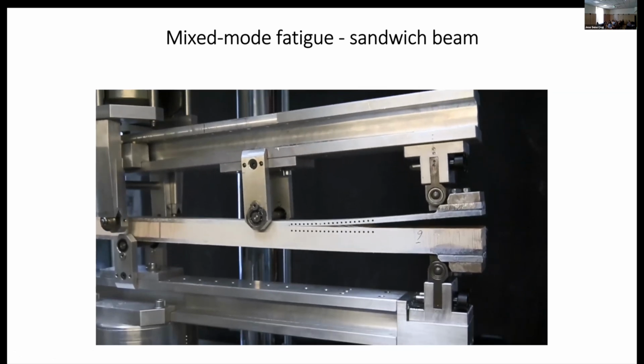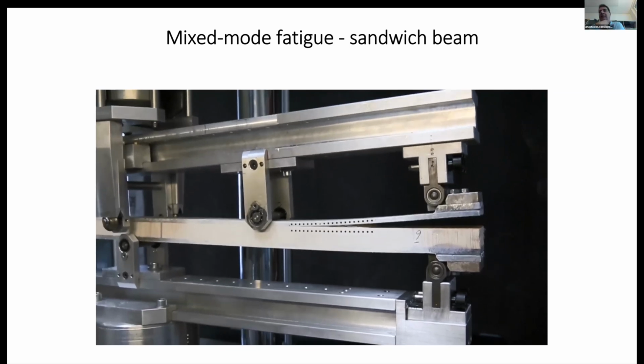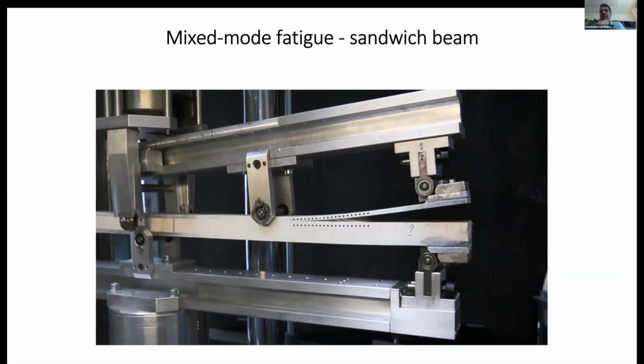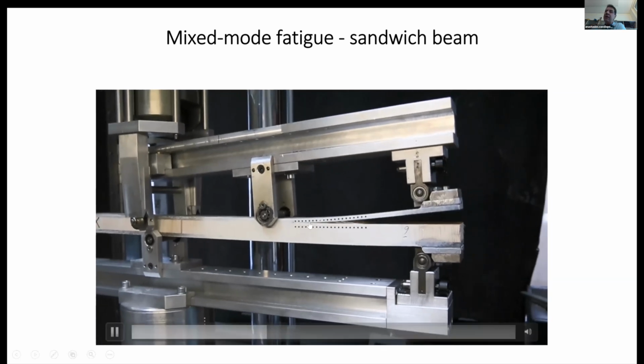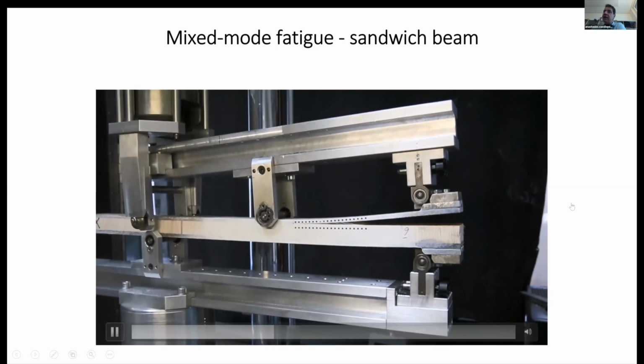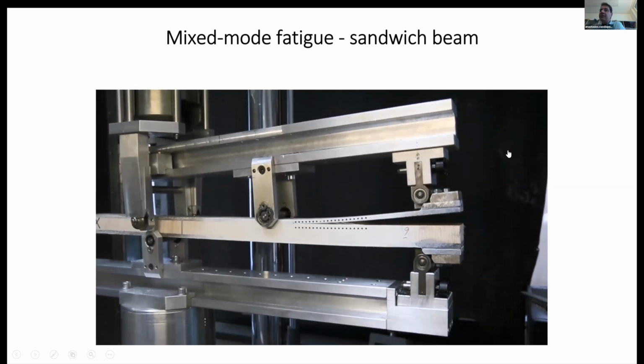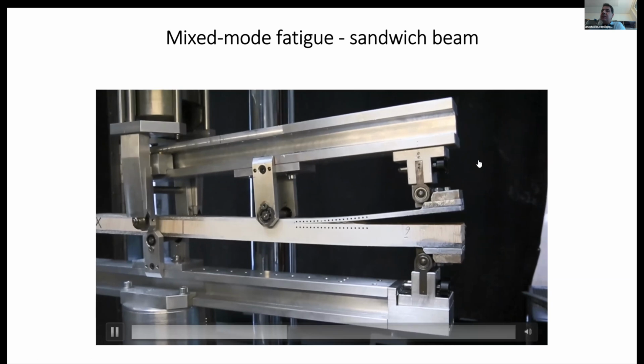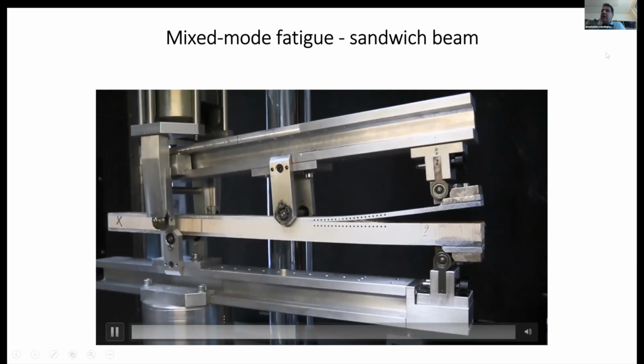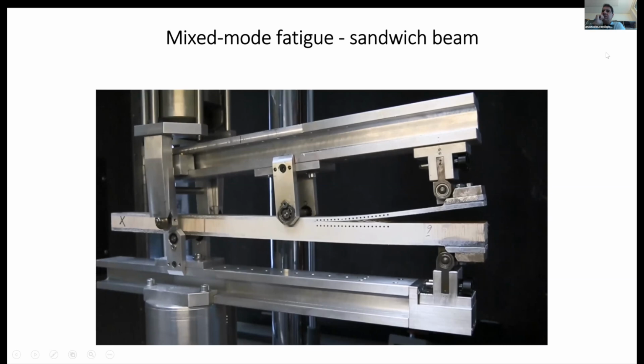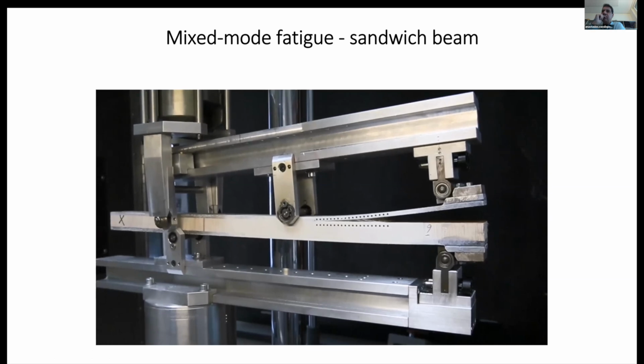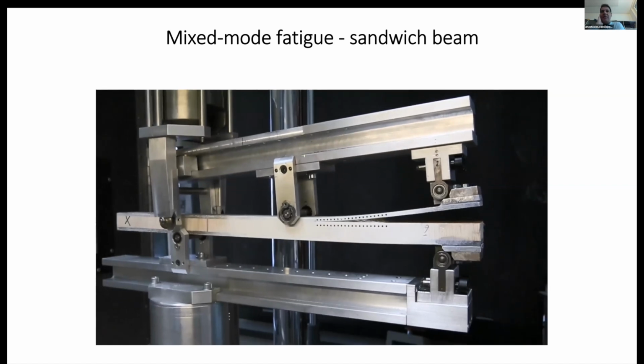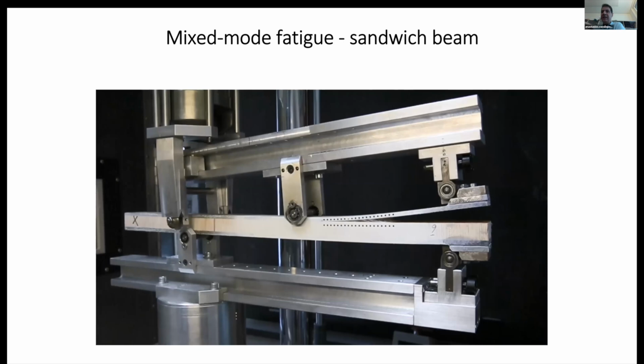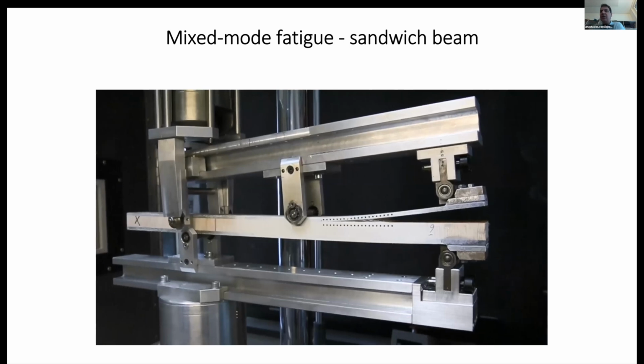So if you are interested in fatigue, you have to be patient and wait until this structure here reaches 2-3 million cycles. And at the same time, you have to be patient to go there and measure the crack. So this was at 5 Hertz. And now we change the loading frequency to 10 Hertz.